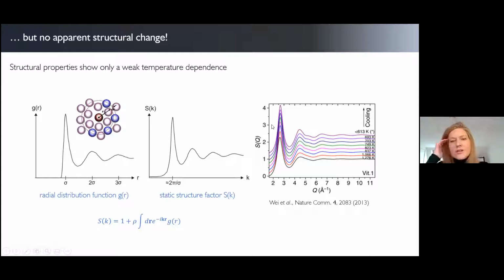And now on the right, you see what such a static structure factor looks like for a real glass forming material as you go from liquid to glass. So the bottom curve is a liquid and the top one is the glass. And these structure factors are all plotted with a little offset so that you can see the difference. But actually, if you look closely, you will see that there is hardly any change happening in the structure. There are very small, subtle changes in the structure, but nothing a priori that would tell you that the viscosity is changing over 15 orders of magnitude here as you go from the bottom curve to the top curve.